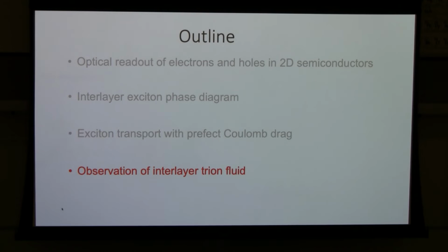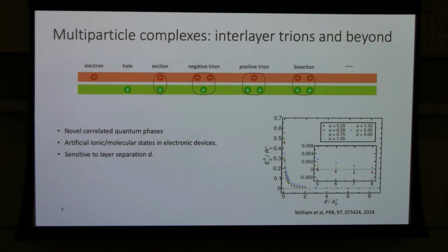Okay, so last I will tell you that beyond excitons, we can also look at multiparticle bound states such as interlayer trions, and maybe possibly beyond. In principle, if we have both attractive and repulsive interaction, as I mentioned, one can form trions, biexcitons, and so on and so forth. However, these multiparticle states become more and more sensitive to the layer-layer separation. Because if you think about the exciton, they are always attractive. So if the layer distance becomes larger, you just decrease the attractive potential by 1 over r. So it has strong distance dependence, but it's more manageable.